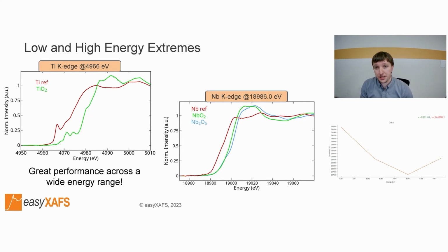For this slide, we are showing specific examples of the low and high energy range of our systems. At the lower end of the energy range, we have a titanium reference metal versus TiO2, where we see a shift related to oxidation state. Additional features of the TiO2 line shape indicate that this sample has the rutile structure. For the niobium K-edge at 19 keV, we're able to differentiate niobium metal and niobium 4+ and 5+ oxides. These two examples highlight the sensitivity of the XAFS technique across elements.